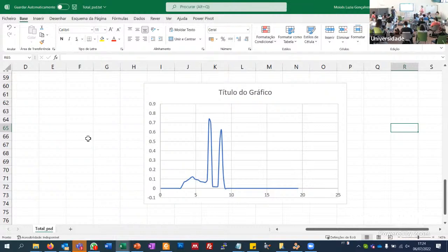And I think the important thing is with this tool, you can have a theoretical structure and then compare with your experimental data, and you can calculate also pore size distribution from the experimental data, micropore volumes, and so on. And if you compare with these theoretical calculations, based, of course, on the crystalline model, if you have some mismatch, this can guide you for some problems that you have in your sample.